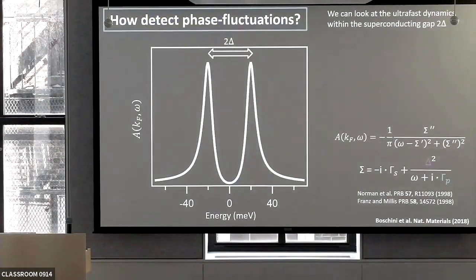based on this model of the spectral function, in fact, Andy has worked on it back in the day with Marcel Franz. So here is a spectral function with a self-energy which takes into account the two parameters, the superconducting gap and the phase coherence itself, or the phase fluctuations. Those would both go in the self-energy. What would the spectrum look like in the case where one is dominant or the other is dominant? So here is the spectral function shown about the chemical potential. Keep in mind in photoemission you will usually only measure the occupied part, but this is simply how you define it. Two peaks separated by a gap, 2 delta.